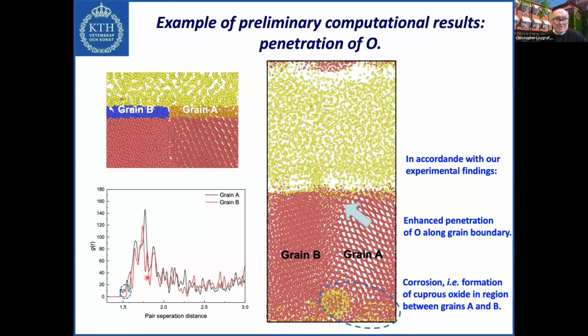We can also see, through something which is quite complicated, the pair separation distance between different species, between different elements in grain A and grain B, that in grain B here you have something along a distance which is quite close to cuprous oxide, and which suggests, as you can see also here, deep into the material, that as a result of the enhanced penetration of oxygen, we form cuprous oxide in a region between grain A and grain B.